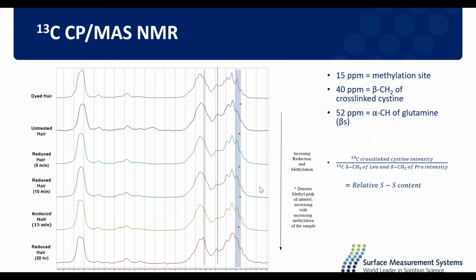And that's likely due to the fact that we did not use any carbon-13 methyl iodide. We didn't use any labelled methyl iodide, and that would have really enhanced this peak for us to make some calculations. However, that's okay. We can still get a lot of information from these spectra.